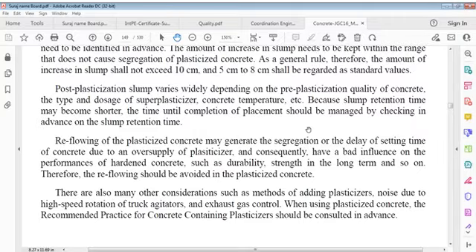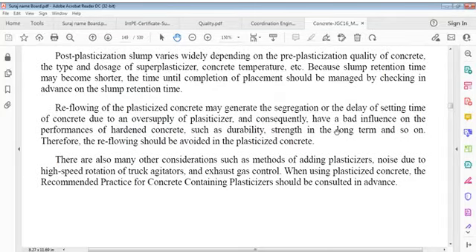Post-plasticization slump varies widely depending on pre-plasticization quality of concrete, type and doses of superplasticizers, concrete temperature, etc. Because slump retention time may become shorter, time until completion of placement should be managed by checking in advance on slump retention time. Reflowing of plasticized concrete may generate segregation or delay of setting time of concrete due to an oversupply of plasticizer and consequently have a bad influence on performance of hardened concrete such as durability, strength in long term and so on. Therefore, reflowing should be avoided in plasticized concrete.